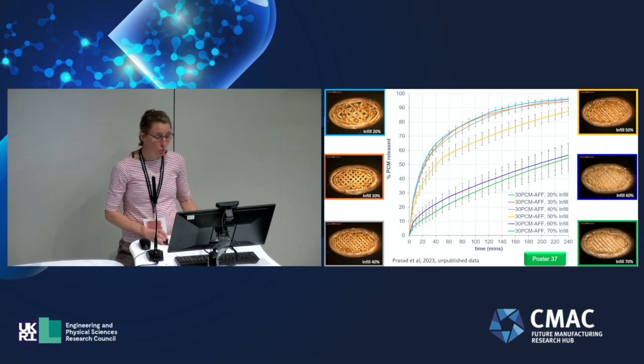And once we get to 50% infill, which is the data points in yellow, we're actually noticing a decrease in the drug release, and this is because now the swelling of the polymer is actually closing up the pores, reducing the drug release from the porous structure of the tablets. And then if we increase the infill percentage of these tablets even further, they behave like a solid block because of the swelling of the polymer.